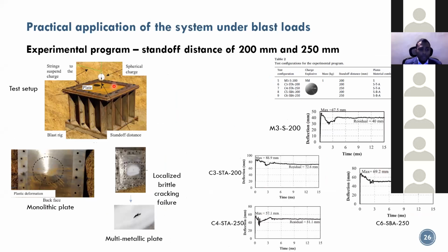We also tested it when the blast source was slightly away, about 250 millimeters away from the plate, and this way of course the damage is much less. But what was interesting about this experimental setup was that we were able to get real-time deflection histories. We inserted an instrument inside what's called the blast rig here. This is a charge, this is the plate. So you explode this, then the plate will deform, and we measured the deflection using a deflection measuring instrument that was placed inside. So we were able to capture the variation of deflection with time. So once again, within a matter of milliseconds, all this happens.